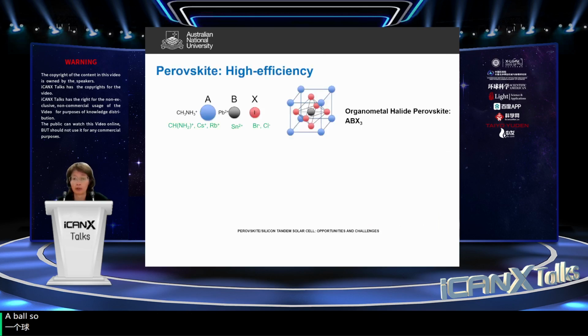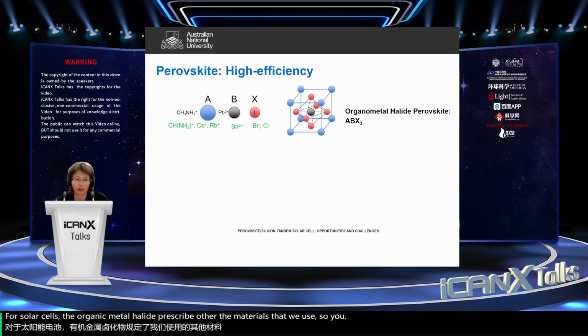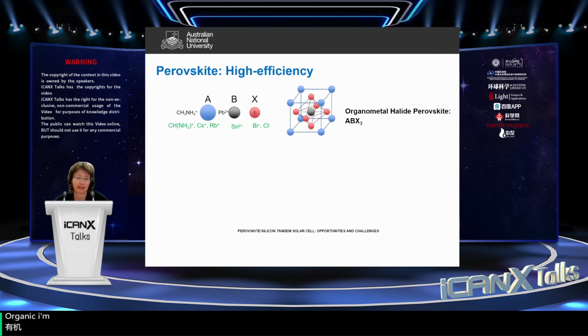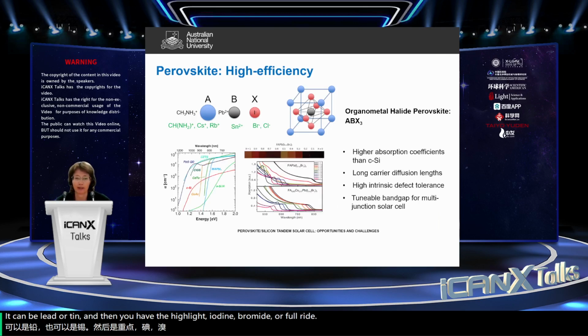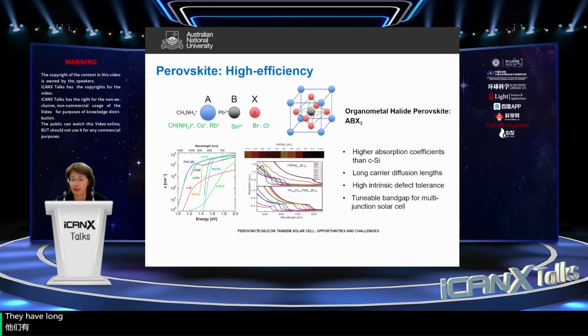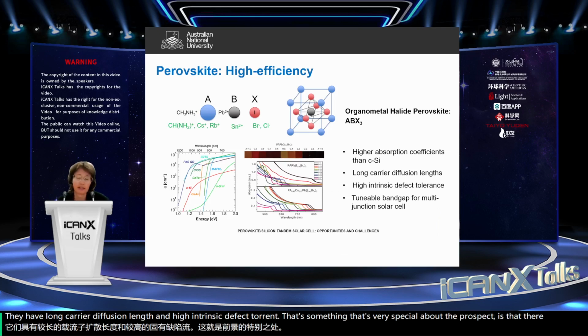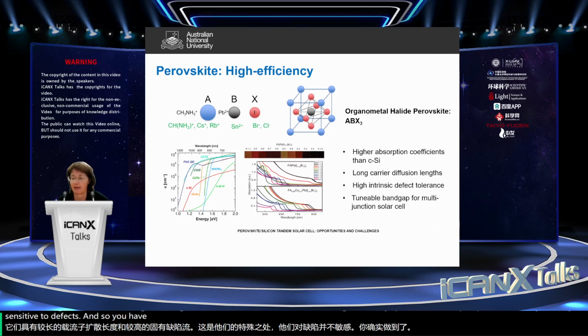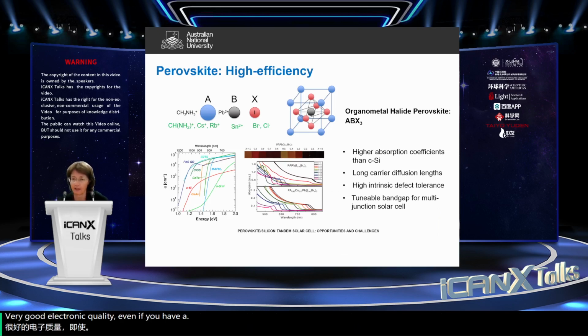For solar cells, the organometal halide perovskites are the materials that we use. So you generally have an organic cation together with other cations, cesium, rubidium. You have the metal, which can be lead or tin, and then you have the halide: iodide, bromide, or chloride. Some of the special things about perovskites is that they have a high absorption coefficient because they're direct bandgap materials. They have long carrier diffusion lengths and high intrinsic defect tolerance. That's something that's very special about the perovskites, is that they're really not very sensitive to defects. And so you have very good electronic quality, even if you have quite a defective material.